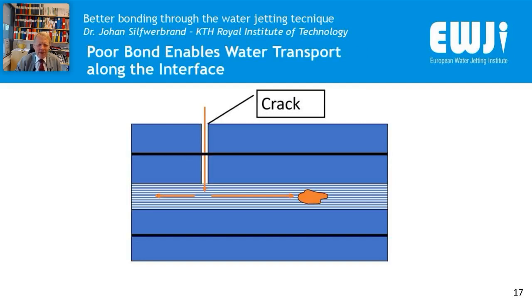And here is a final slide about the importance of receiving good bond. You can see here that if we have poor concrete in the interface zone, then if there is a vertical crack, water will penetrate to this interface, and then it will have a transport road to pores in the poor concrete. And then when the water is freezing during winter time, we can have frost damages. So this is a fourth reason to receive good bond and remove all bad concrete.